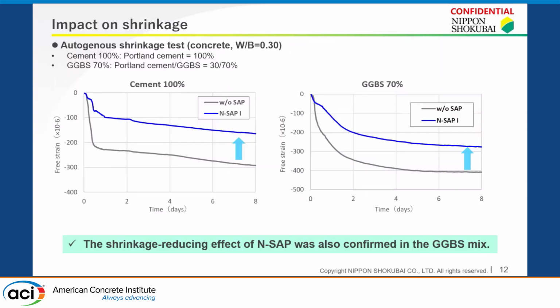Now let's turn our attention to the impact of SAP on shrinkage. From our original shrinkage test with two different mixes, one with 100% portland cement and another with 70% GGBS, this data shows our new SAP1 can minimize autogenous shrinkage in both mixes. So yeah, previous studies have reported SAP can reduce autogenous shrinkage, and we confirmed our new SAP also has good properties to reduce autogenous shrinkage.